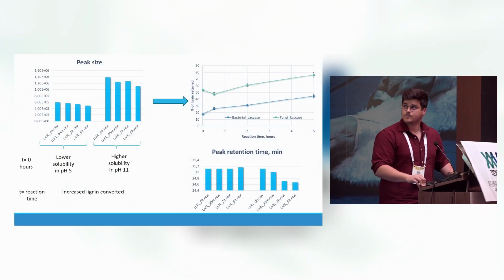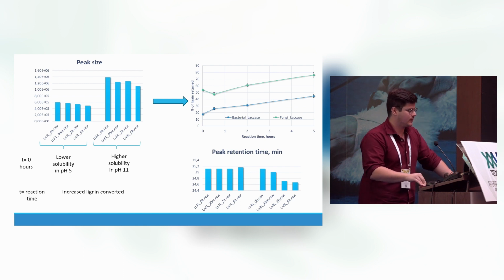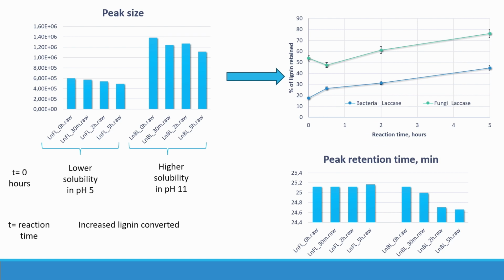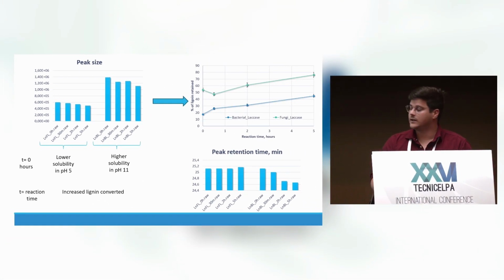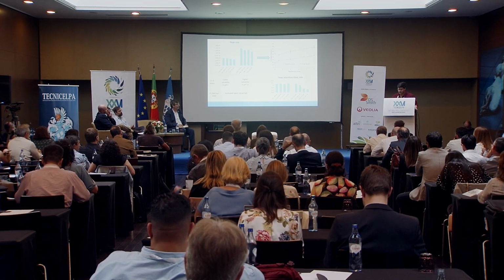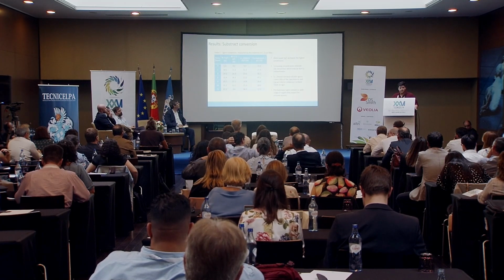What we see is, we can start with the peak size, the signal of the method that we studied. We can see that the lignin at pH 5 has inferior solubility. By this means it is less reactive for the treatment employed. On the other side, we have higher solubility at high pH. These results are in agreement with the filter measurement, where we can see that with the inferior pH used, we have higher lignin retained from the 0 reaction time. As I mentioned before, one of the main differences is the retention time of the lignin peak, and we can see that with the bacterial LACCASE we have a decrease of it, representing the increase in molecular weight.